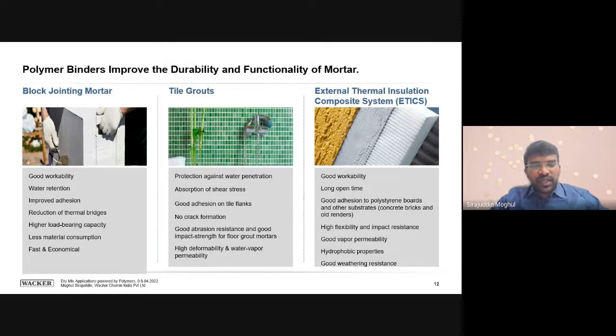So if it doesn't have to allow water to penetrate, if it's a normal cement sand, what is... see, in the traditional way, what they do is they take cement, make white cement, mix water into it, and then apply it by finger. That is how they do it. But this is not waterproof. What happens is water penetrates underneath through this grout, and then tiles will start to come off.